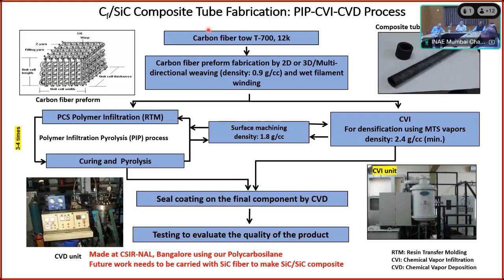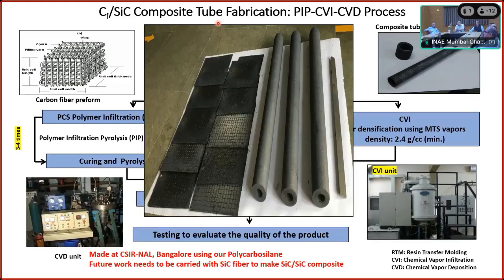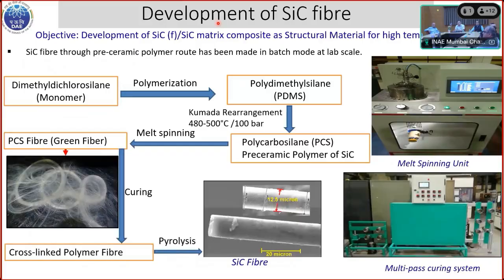So we have done the work shown on the right side. You can see this is nearly a 1 foot long rod, and it has all the structure in it. First the carbon fiber skeleton, the preform, is made, and then we infiltrate silicon carbide into that by a completely new method. This is not new for NAL and CSIR, because they were making caps for ISRO. So we have taken their help and made this material. But then the requirement later was changed. The material they first asked for has already been made and is available with us, and they wanted the silicon carbide fiber to also be made. So now we are moving from carbon fiber to silicon carbide fiber, with a silicon carbide matrix.